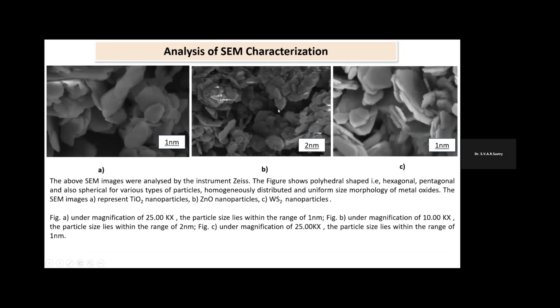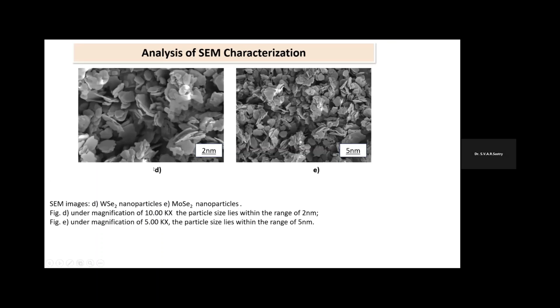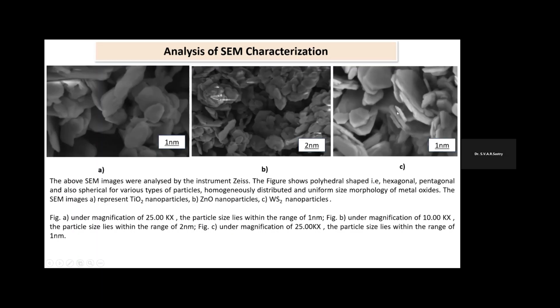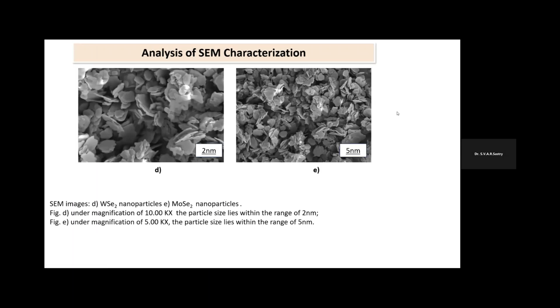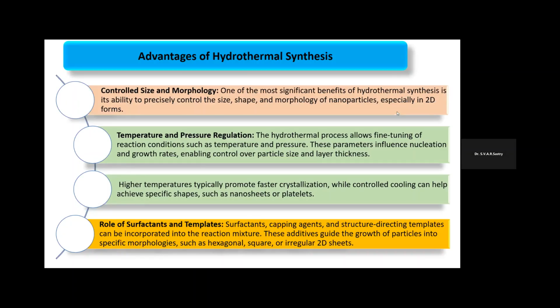Then we have ZnO nanoparticles and tungsten disulfide nanoparticles. It was observed that we had good nanoparticles formed with good morphology. Similarly, this image shows tungsten diselenide nanoparticles, and here we have molybdenum diselenide nanoparticles. So everywhere, for all the 5 different samples, we saw good yield and good morphology of the formed nanoparticles. So now let's see the advantages of the hydrothermal synthesis method.